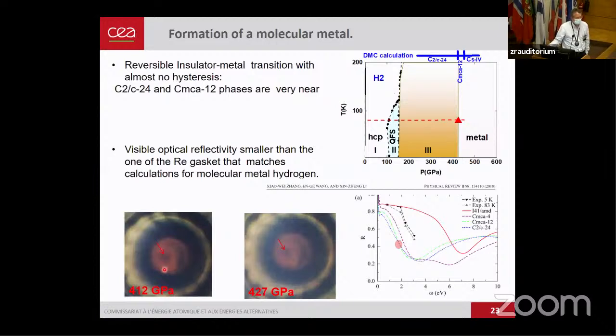Question from Angelique Carosa. Do you expect a similar band gap closure behavior for hydrogen-deuterium mixtures? If it's a mass effect, it will be in between, but it's not so interesting. It can be very interesting if we want to disclose some quantum effect due to the spin of the system. If there are some magnetic properties of this metallic hydrogen, as have been predicted and calculated, this will be more difficult with very low temperature measurements at extreme pressure. Probably then we'll have to do some mixture, but it's not the first measurement to be done.